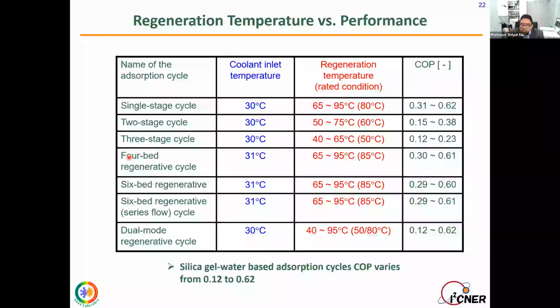Then we have 4-bed regenerative cycles, from which we can get a little bit higher COP values. And finally, I showed the performance of the dual mode cycles. It can operate from 40 to 95 degree heat source temperature. In the single stage mode, usually 80 degrees is the rated condition. For 3-stage mode it is 50. And then COP also varies from 0.12 to 0.62.